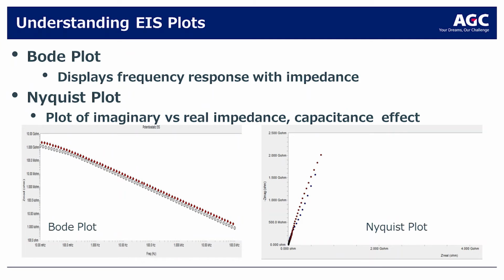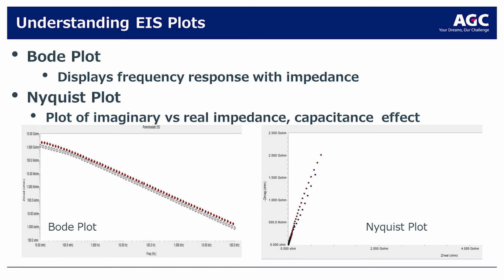There are a couple of different things we can do. We can do a Bode plot, which is on the left, and that displays the frequency response with impedance. The Nyquist plot is a plot of imaginary versus real impedance and the capacitance effect. What you're really looking for in Nyquist is that the y-axis is a perfect capacitor. So over the exposure time, you want your coatings to be as close to vertical as you can. You want those readings in that graph to be as close to vertical as you can get it.